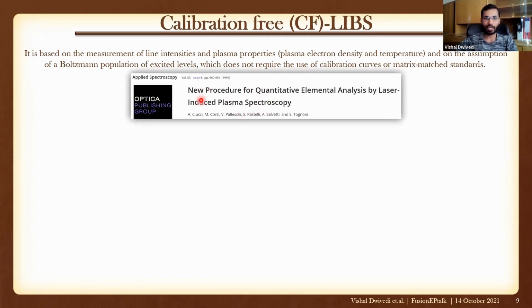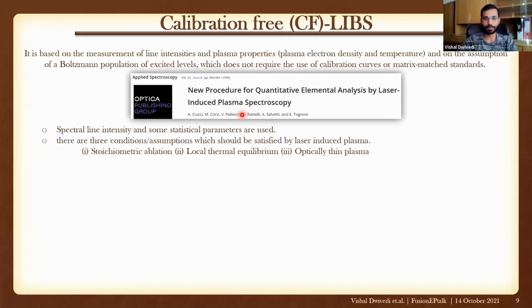Historically, it started from this paper, 1999 Ciucci, "A new procedure for quantitative elemental analysis by laser-induced plasma spectroscopy." This paper tells that spectral line intensity and some statistical parameters can be used for the CF-LIBS quantification. There are three important assumptions which should be satisfied by laser-induced plasma in order to use the CF-LIBS technique. These three are stoichiometric ablation, local thermodynamic equilibrium, and optically thin plasma.